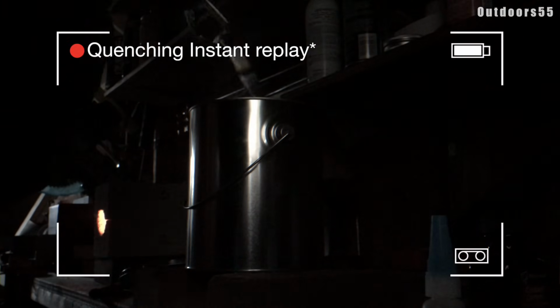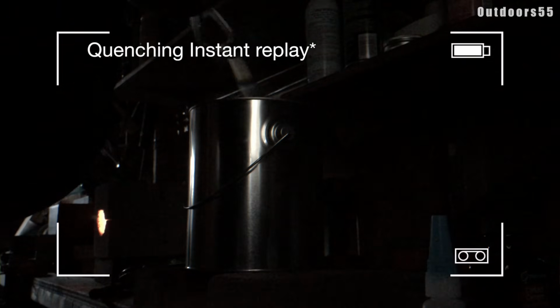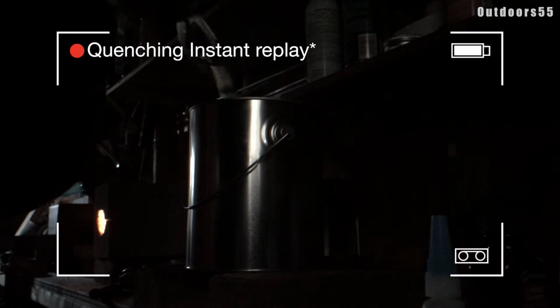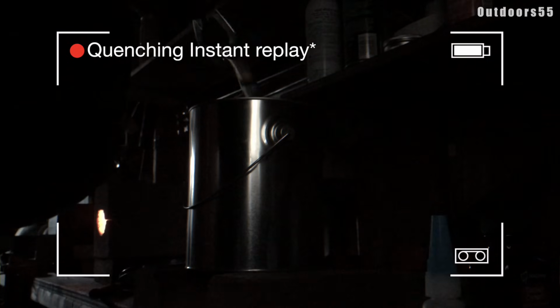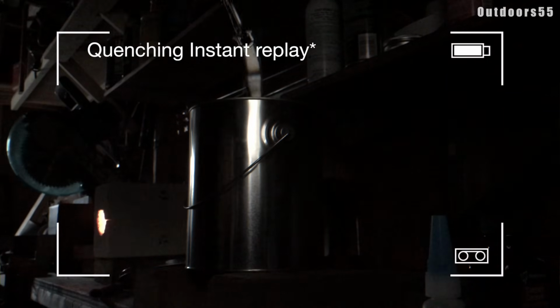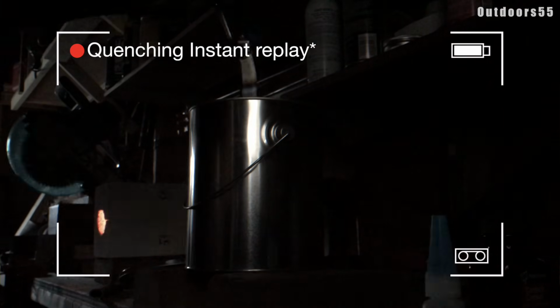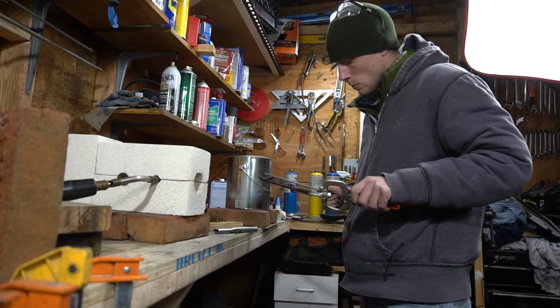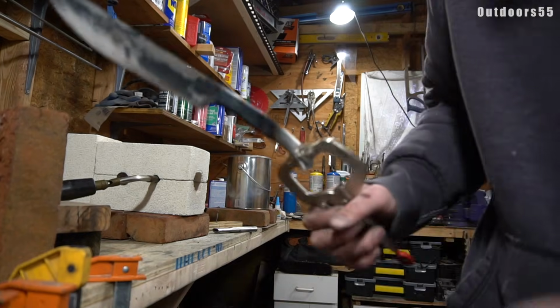1080 needs to be cooled at a very fast rate in order for it to harden. Now, you technically can use water to quench 1080, but water is a very violent quench. It can cool the steel too fast and cause a crack, which is not good for knives. Now I'm not saying water can't be used without cracking, but the risk is much greater than with oil.